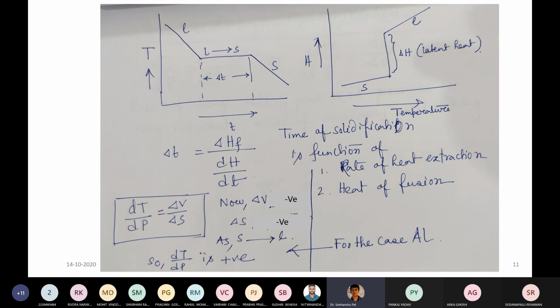So if you check here, now there is a latent heat, and suppose liquid to solid transformation is occurring, so there is a delta T. So the time of solidification is important, that you have to have a certain time to change all the liquid to solid, and also the latent heat is important. For the time of solidification, you can check it as a function of rate of heat extraction and heat of fusion. Delta t you can write as delta H_F by dH by dT. So the solidification time is a function of the rate of heat extraction, how quickly you can extract the heat, and that helps you to solidify the material as soon as possible, and also the amount of energy to be extracted, in the form of heat of fusion, is very important.